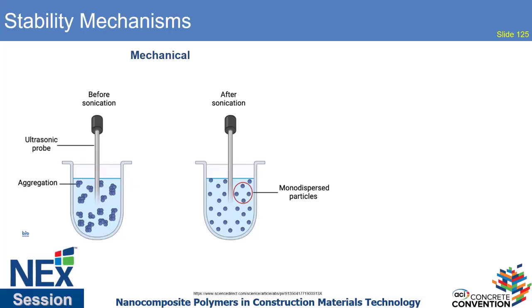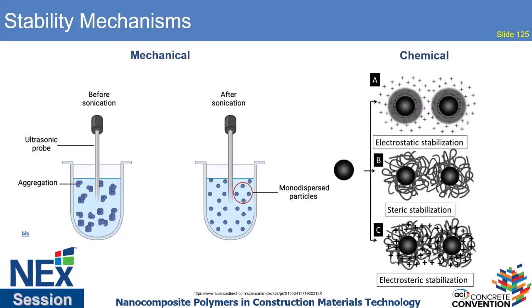However, I also want to mention when we talk about powder pigments that besides sonication, the wetting out of the pigments plays a crucial role. Sonication is not sufficient to wet out the titanium dioxide nanoparticles. The other is the chemical stabilization. When we talk about chemical, there is electrostatic stabilization, steric stabilization, or electrosteric stabilization, which is a combination of the first two. Steric stabilization is also known as polymeric stabilization or nonionic stabilization, when nonionic surfactants are used, and usually polymers get adsorbed on the surface of the particle and the repulsive forces are formed.